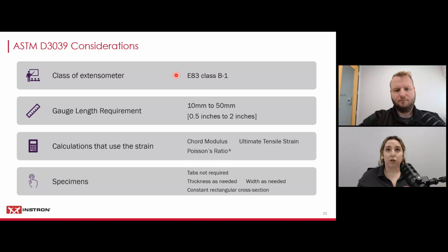So I used a 2-inch 10% elongation clip-on, not verified, but that's okay. But if we were to have this verified by a service engineer, you have a better chance of getting it classified as B1. So again, if you are using a clip-on, you want large gauge length, low elongation. That gauge length requirement from the standard, you can do from 10 millimeters to 50 millimeters or 1/2 inch to 2 inches.